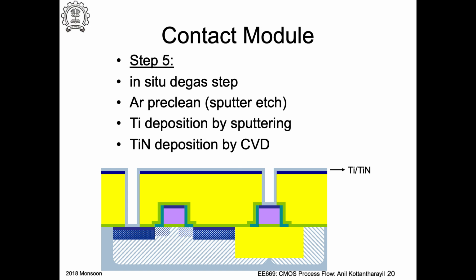So why is the diffusion barrier important? Because you're going to put tungsten, copper, and all the stuff on top to create this wiring between the transistors, right? So the copper should not diffuse into the transistors, right? Source drain regions. So I want to prevent the diffusion of this. So that's why you're going to use a diffusion barrier. Titanium nitride is a very popular diffusion barrier.